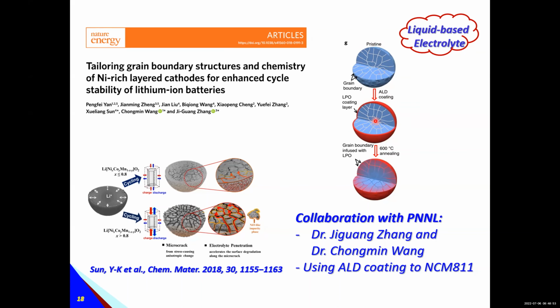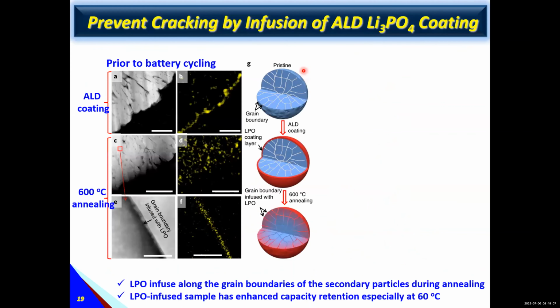After coating, we try to have a simple annealing to put this coating material into the grain boundary to try to prevent the cracks along the grain boundary. So we use ALD to synthesize lithium phosphate. The coating on the particle, we see that is phosphate signal. The signal here, after a simple annealing, is penetrated inside. If you look at details at the grain boundary here, we still have the phosphate signal along the grain boundary. So that means the coating material penetrates into the grain boundary.